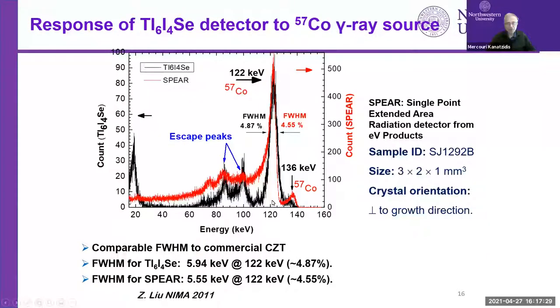The spectrum in black is our compound, this new compound. And for comparison, the spectrum in red is the CZT coming from a commercial SPEAR detector. So we use this as a benchmark, and the black is our material. And it looks excellent, achieving 4.87% resolution, very similar to CZT. The crystal here was 1 millimeter thick. So we got very excited about this, and we started working very hard.